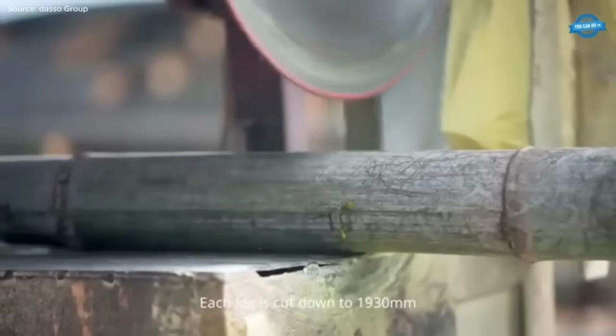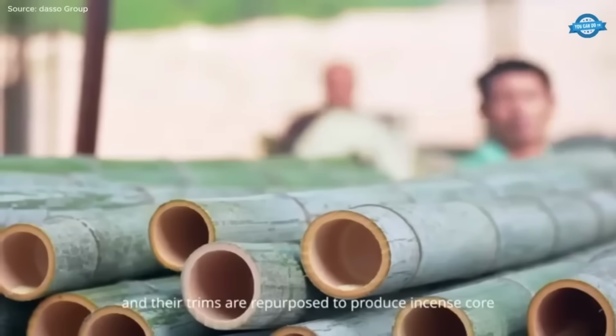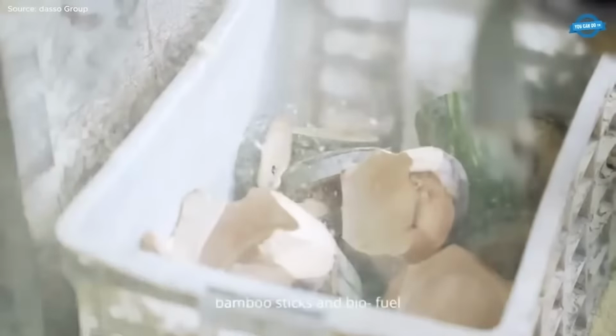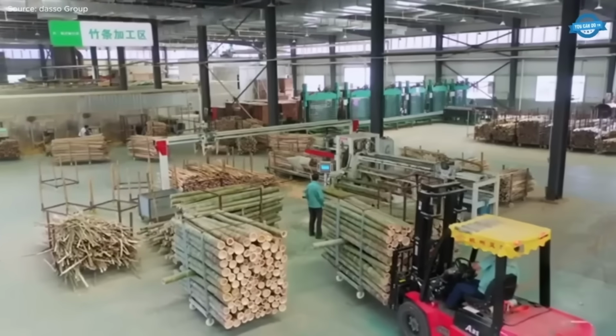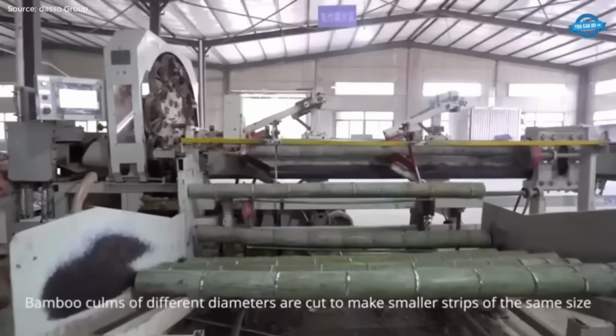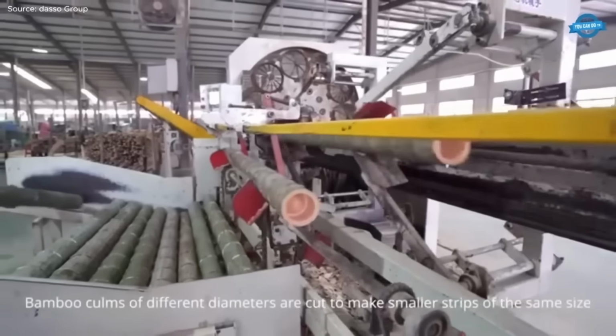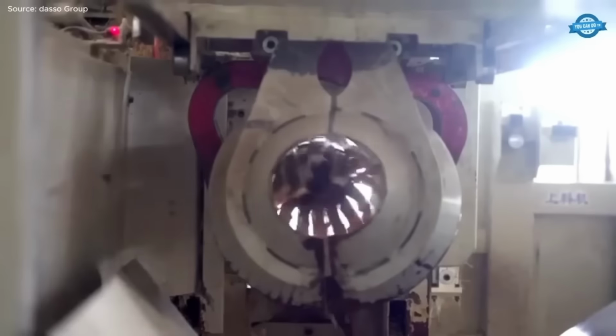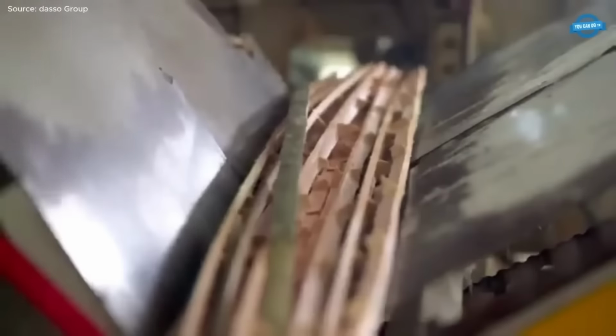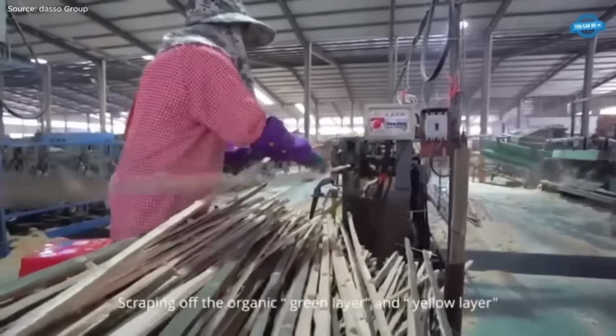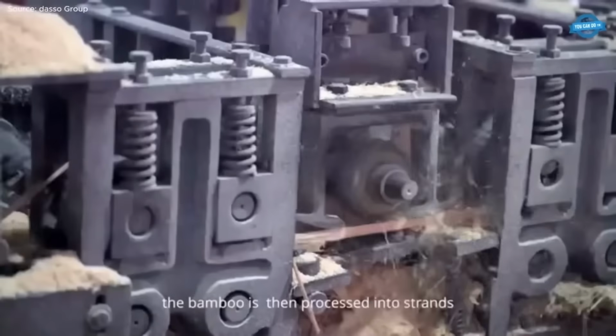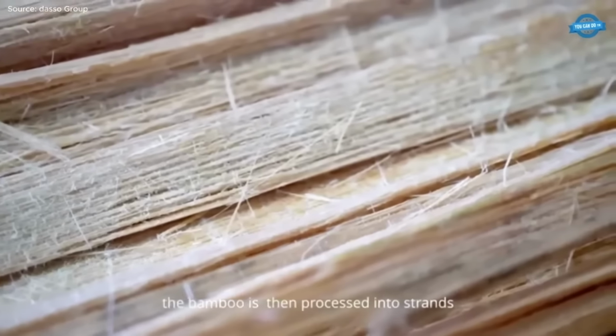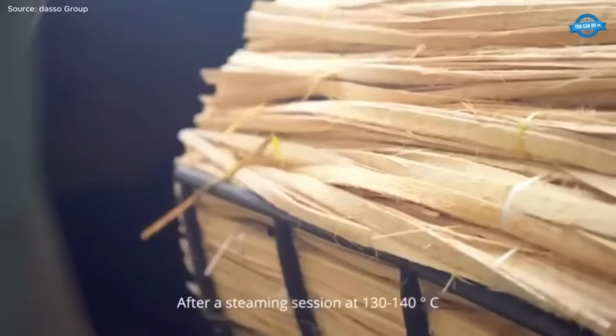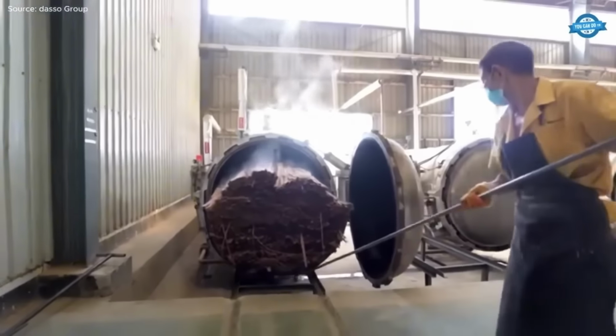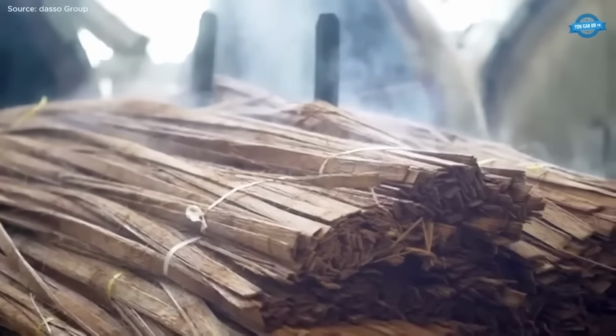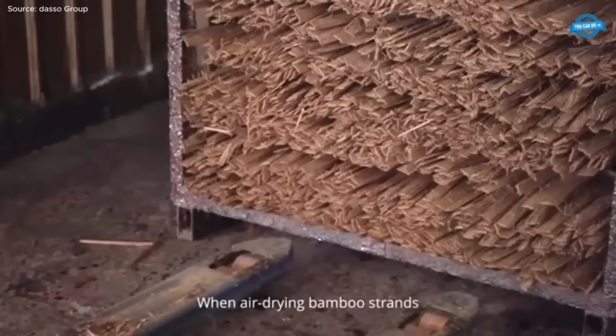Dasso bamboo decking begins its journey on 66.7 million square meters of FSC-certified bamboo farms. Only 4 to 6-year-old bamboo is harvested, cut to 1930 millimeters, with trims repurposed for incense cores and biofuel. Columns of varying diameters are resized, then scraped to remove green and yellow layers. Strands are steamed at 130 to 140 degrees Celsius, carbonized, and air-dried to 6% moisture.